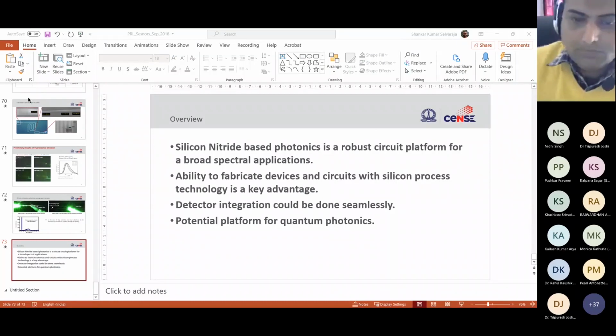Silicon nitride means the bonding in silicon nitride is which type of bonding? Hydrogen bonding or something else? No, there you don't have a problem with the temperature. You have silicon, nitrogen, and hydrogen involved in the network. If your operation goes beyond 450 or 500 degrees C, then your hydrogen starts to get highly mobile. So there you see the thermo-optic effect.